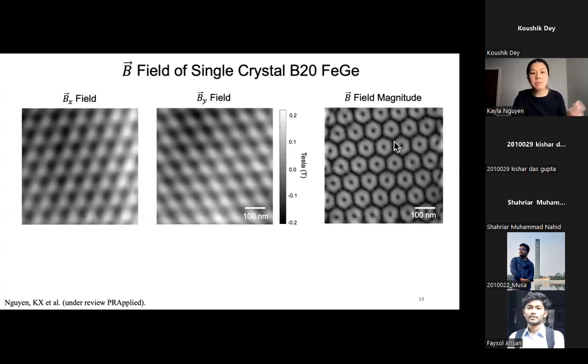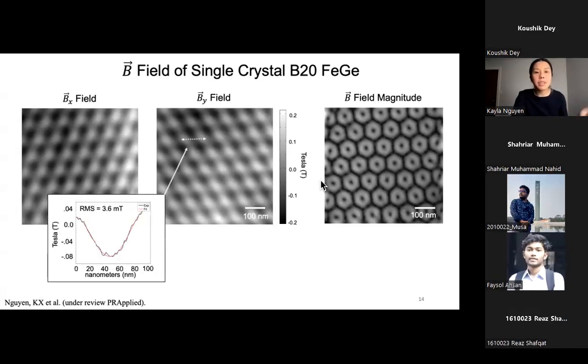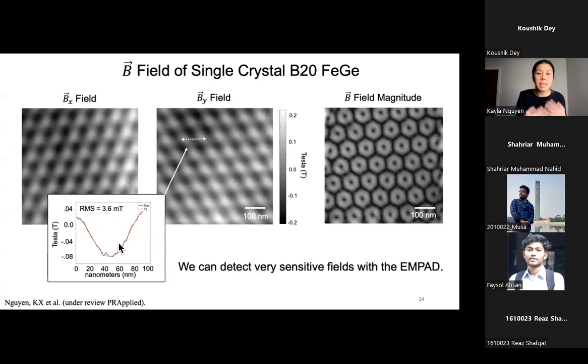And so this is the shape of the skyrmion that we get from our technique. If you take a line profile within the magnetic field image in the Y direction and fit it to a curve, we get a root mean squared of 3.6 millitesla. What this means is that we can detect very sensitive fields with the electron microscope. And this skyrmion is on the order of about 50 nanometers, so we can also look at nanoscale structures within our electron microscope as well.